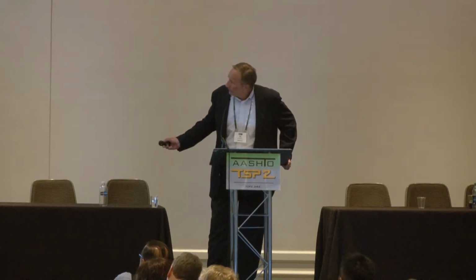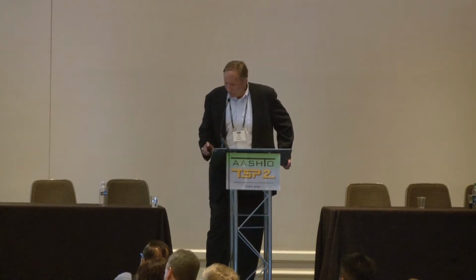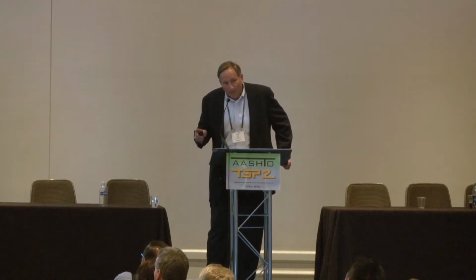And also one of our requirements was to determine, as we remove some of the deteriorated concrete, just how bad or how deteriorated or broken the pre-stressed strands were. And if in fact we found that there were more than 2 in this particular case, or more than 6 in the prior slide, then we had to consult with the engineer of record and the Eastern Federal Lands folks to determine if we needed to add more carbon fiber material.